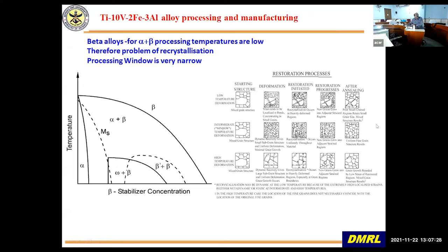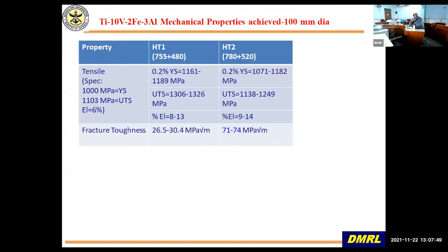Otherwise, you will get a non-uniform structure and you will not get good mechanical properties. So you have to hit the right window, because the temperature, strain rate, deformation, everything has to fall in place. So that is why processing these materials is not very easy. You have to hit the right window, and that you have to identify by doing research and processing, and that takes time.